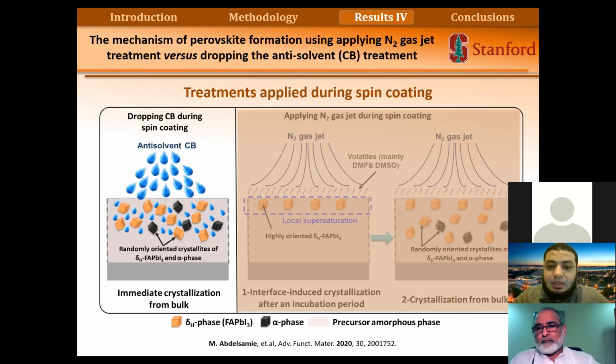Yeah, of course. The choice of solvent is also one way to control the whole thing. So here I'm using DMF and DMSO. If we use only DMF or only DMSO, it doesn't work well. What do you mean by it doesn't work? So the film quality is bad. We end up with a rough film, and the rough film can also have some pinholes. So if you use dual solvent, I think the dual solvent itself is better.